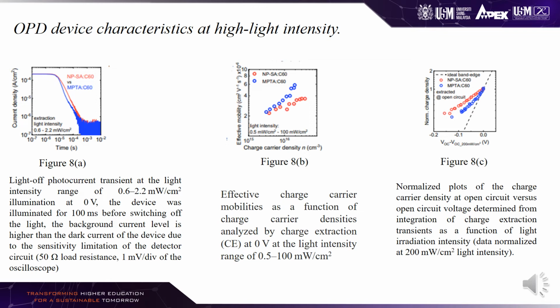Figure 8b shows the effective charge carrier mobilities as a function of charge carrier densities analyzed by charge extraction at 0 volt at the light intensity range of 0.5 to 100 milliwatt per centimeter squared. Figure 8c shows normalized plots of the charge carrier density at open circuit versus open circuit voltage determined from integration of charge extraction transients as a function of light irradiation intensity.